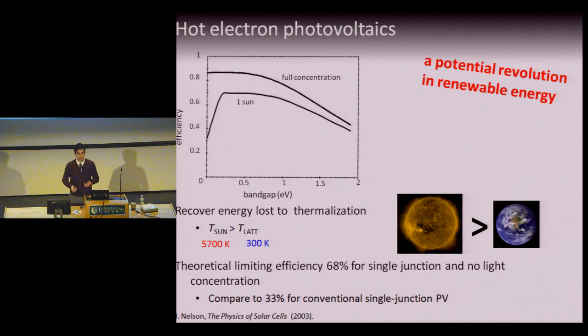In practice, this is very difficult to do because the photo-generated electrons and holes in a semiconductor, which start out at time equals zero with this thermal signature, very quickly cool to something approaching this temperature. And in the process of doing so, it knocks down your theoretical limiting efficiency significantly from 95% to something close to 33%.